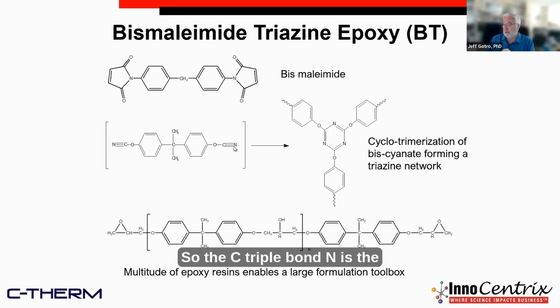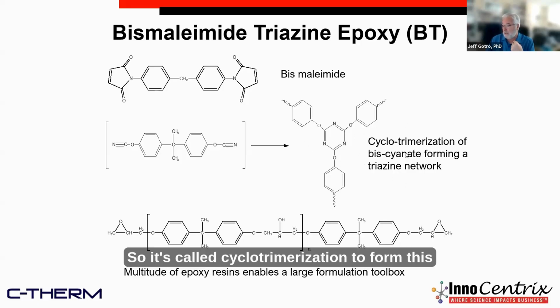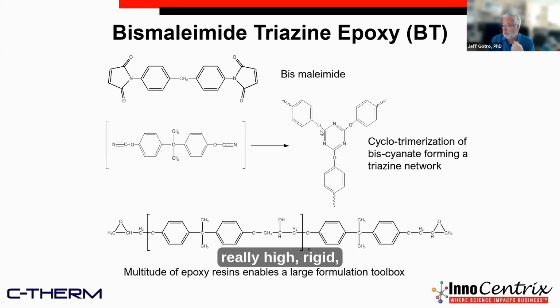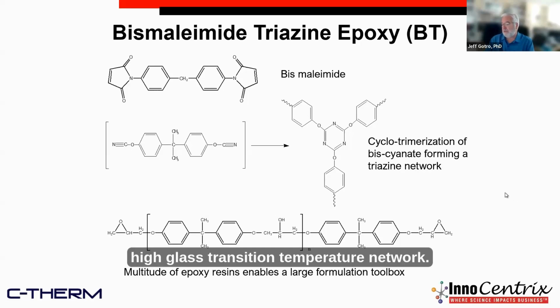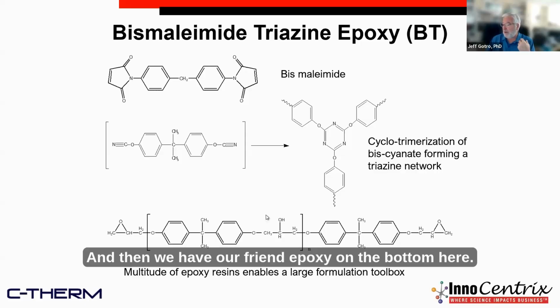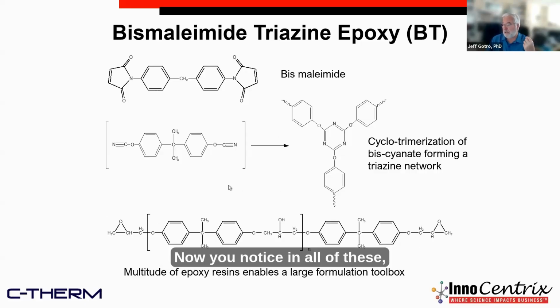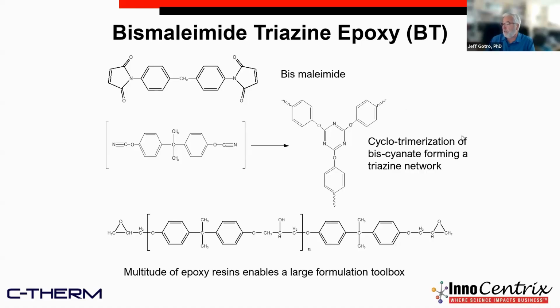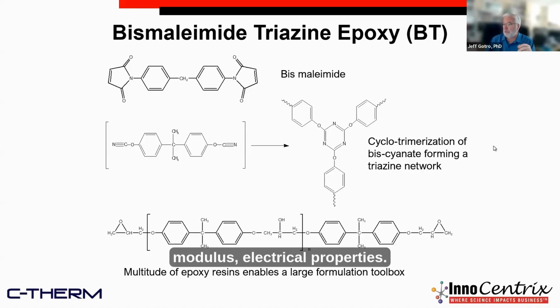Then we have this cyanate molecule. So the C triple bond N is the dicyanate. There's one on each end. And that forms these cyclic rings. So it's called cyclotrimerization to form this really high, rigid, high glass transition temperature network. And then we have our friend epoxy on the bottom here. Now you notice in all of these, they have reactive groups on each end, right? And so now by tailoring the ratios and the types of material you put together, you can form some very interesting and specifically tailored glass temperature, modulus, electrical properties.